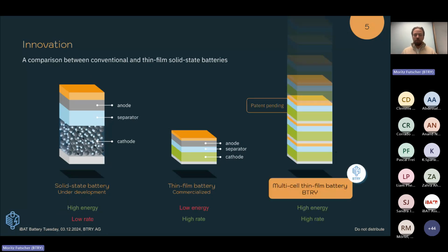And what we have been working on, and what our vision is based on, is really to now combine the benefits of both. So to increase the amount of cathode per substrate while not losing the high rate performance of these thin film batteries. And we can do this by stacking several of these thin film batteries on top of each other, on top of the same substrate. This means basically that we reduce the weight component of the substrate, and with each cell we are reducing the total weight component of the substrate. And doing this allows us really to combine high energy and high rate.